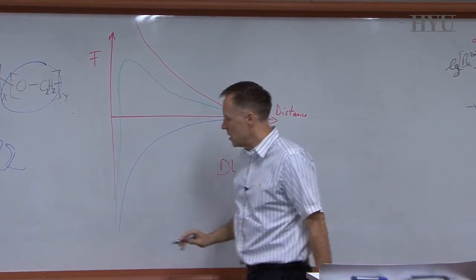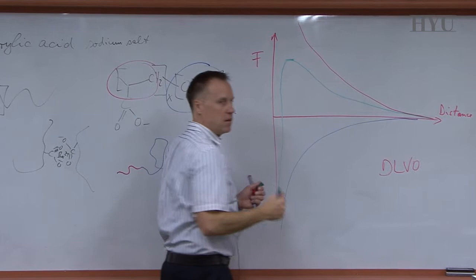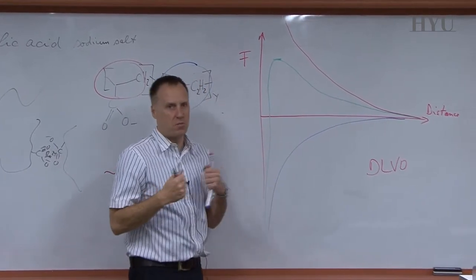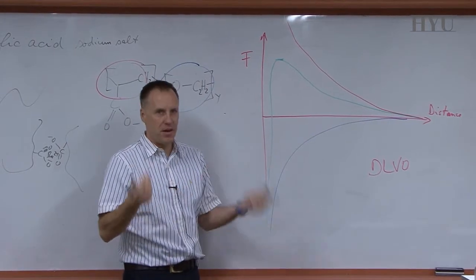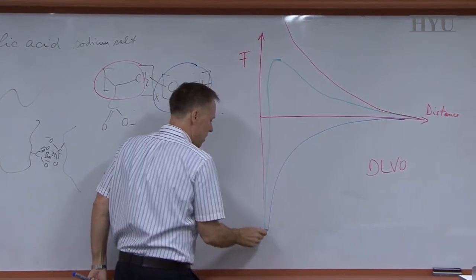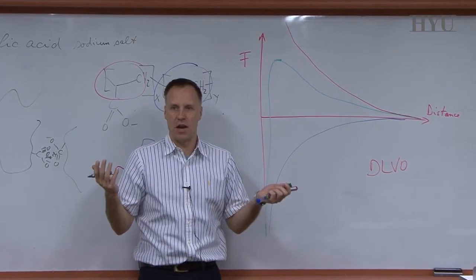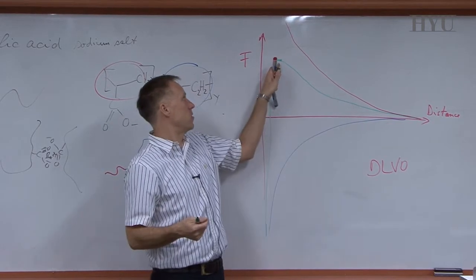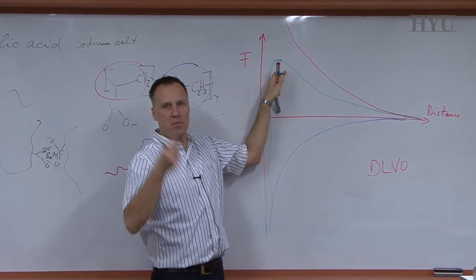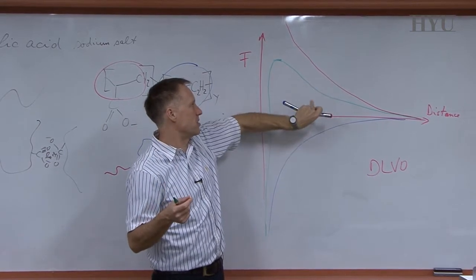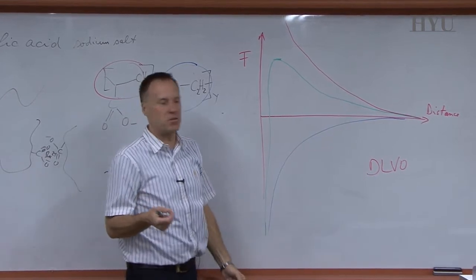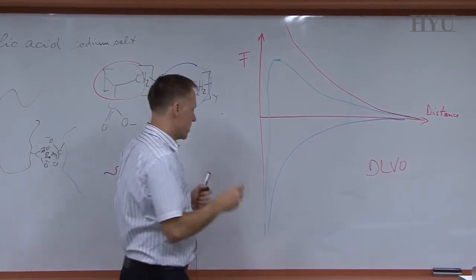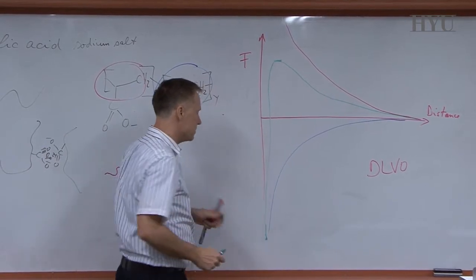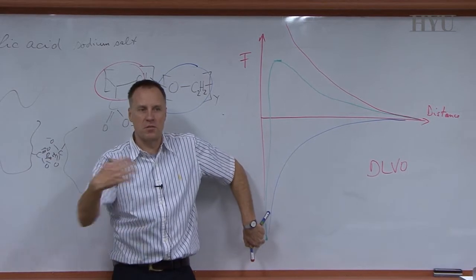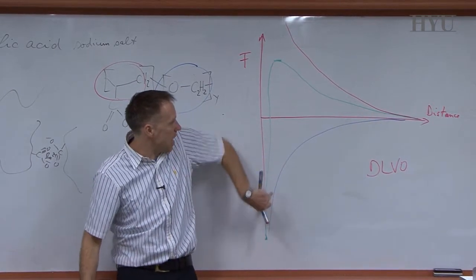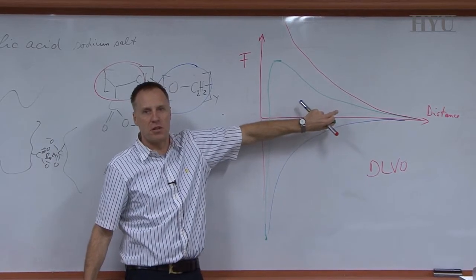So for DLVO, it always means there is a barrier formed. And then when you push it over the barrier, which if the barrier is too high, you can't push it over. But if the barrier is not so high, you can push it over. But let's say if you evaporate the solvent, or if you have water in the system and evaporate the water, of course, you're going to go over this barrier. Because first of all, when you evaporate the water, the ions that are present will concentrate, that will compress your double layer. So at some point, there's nothing there to repel anymore, so you stick. And so you can actually come to this primary minimum down here. And if you add water to the system again, it's stuck, because you have to get it out of this back over there. And so you have to put in energy like grinding or milling.